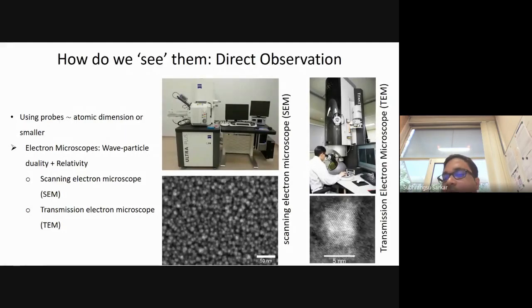On the other hand, if you use a 300 kilovolt Titan electron microscope, you can literally see the atomic columns. This picture on the rightmost side of the slide, on the bottom, is the picture of a nanograin, which has a typical dimension of 5 nanometers. And you can easily identify each atomic column in that figure for that particle. And also, if you look carefully, you will see that this nanograin is not one single particle. It's actually comprising of more than one particle. This is the amount of power or resolution today's electron microscopes can provide you.